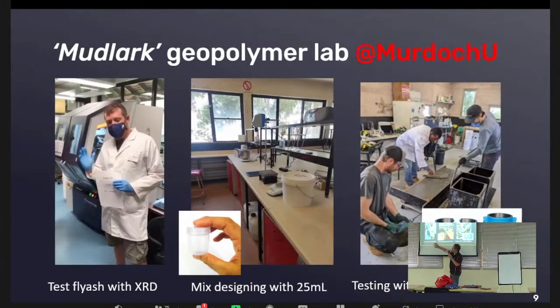So what we're doing in our research is we take the fly ash and we put it into one of the tests in the chemistry department using an XRD machine, X-ray diffraction. And we're analysing the fly ash for the amount of aluminosilicate in there that is amorphous, the proportion that's amorphous versus crystalline. Because if we can find out the amount that is amorphous, we know how much chemicals to use. This is the reactive part. That's what we're looking for by doing the XRD machine testing.